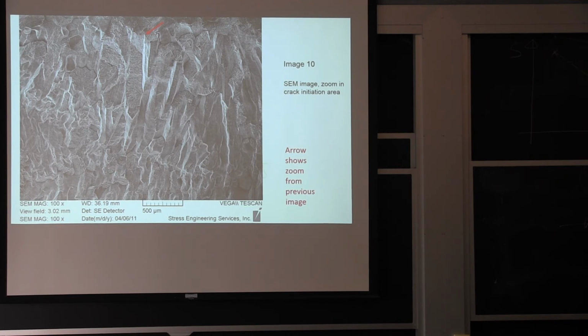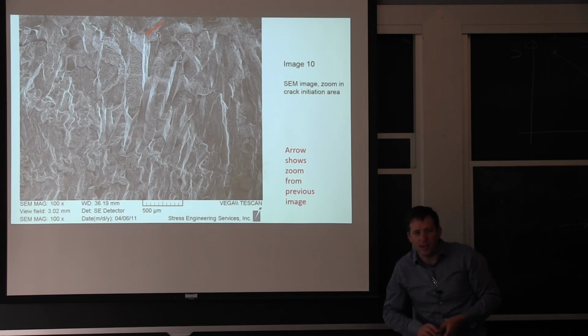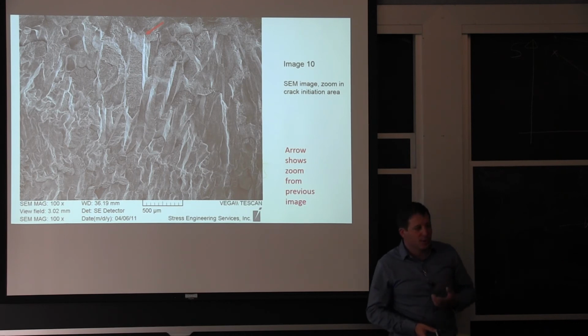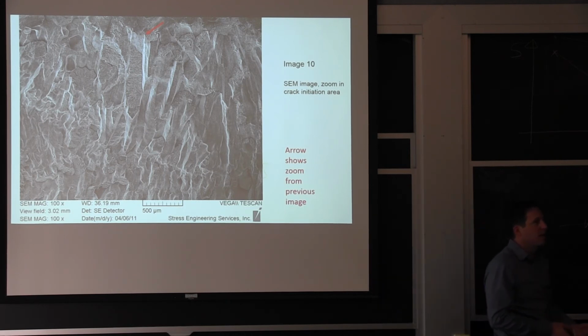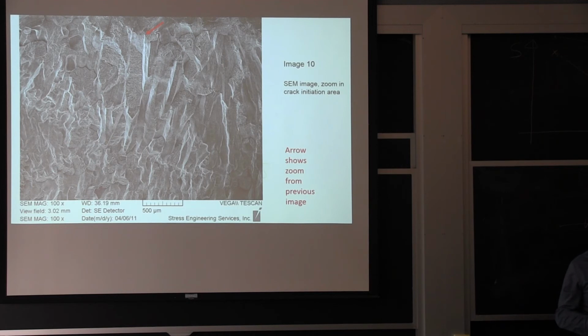These details on the fracture surface are essentially how we can tell that the environment contributed. And that actually goes back to some of our previous discussion about cracking between grains or cracking through the grains and whether the grains are weak or not. So in this case, the grains do become weak because of the hydrogen generated, again, by the combination of cathodic protection applied on the chain and the environment.